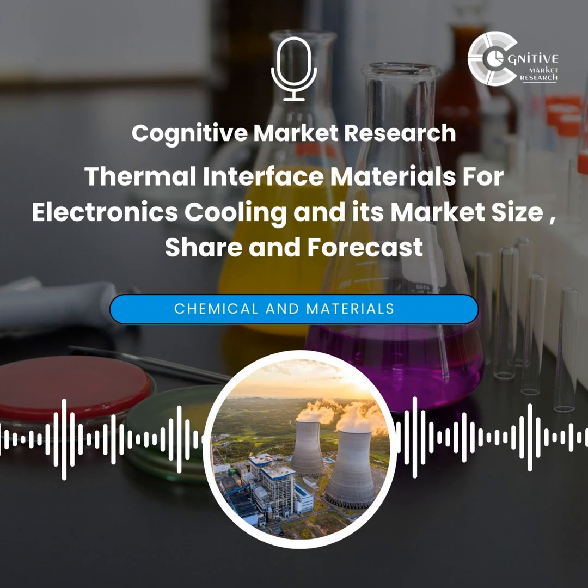Interesting. Okay, cost is one. What else? The report mentioned durability issues. Yeah, that's a really important one. TIMs aren't necessarily a fit-and-forget solution. They can degrade over time. How does that happen? Several ways. Repeated heating and cooling cycles, thermal cycling, can physically stress the material. Mechanical pressure or vibration can cause issues, sometimes oxidation if they're exposed to air. This leads to problems like, the report calls it pump out. Pump out, like it gets squeezed out. Kind of, yeah. The expansion and contraction can slowly push the material out from between the surfaces it's supposed to connect. Or you get dry out, where volatile components in the TIM evaporate over time, leaving it less effective, maybe even crumbly.